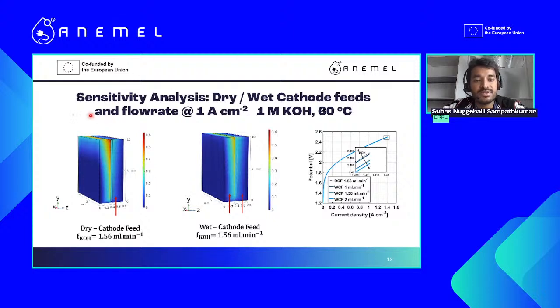There is also a reason for electrolyzers to be operated with only one side fed, similar to the PEM electrolyzers that I showed during the introduction, that we do not send liquid electrolyte on both sides, because the evolving hydrogen would be drier if you send the liquid only on the anodic side. So this study was also performed, and we found out that the effect of dry cathode versus wet cathode is slightly low compared to the other parameters that we saw till now in the sensitivity analysis, predominantly because the membrane has a very good water uptake that humidifies the hydrogen side, where the water molecule is necessary to split and evolve hydrogen.